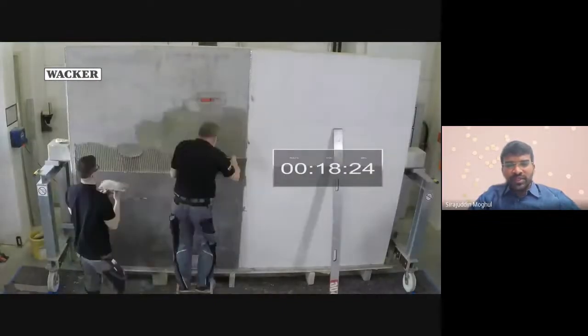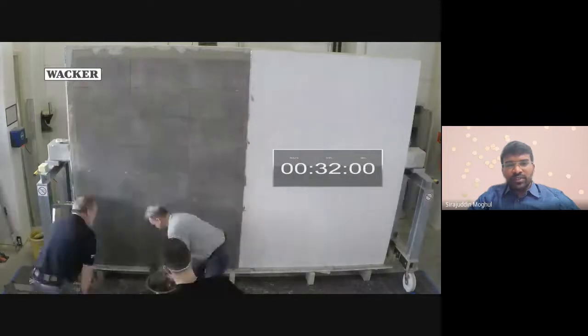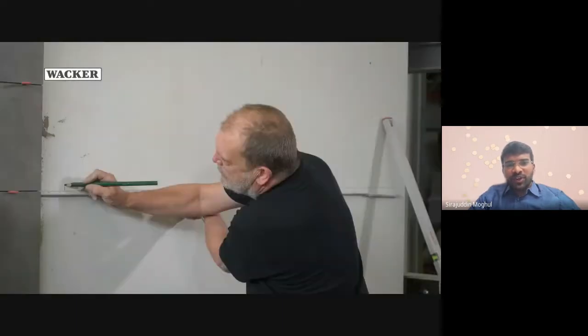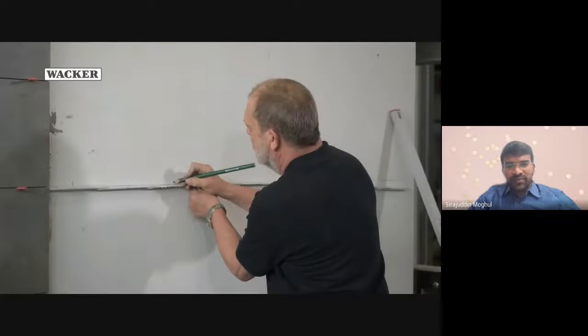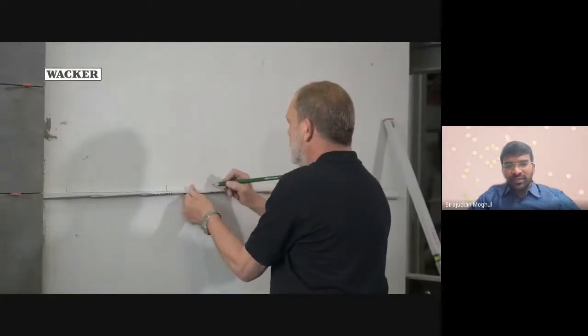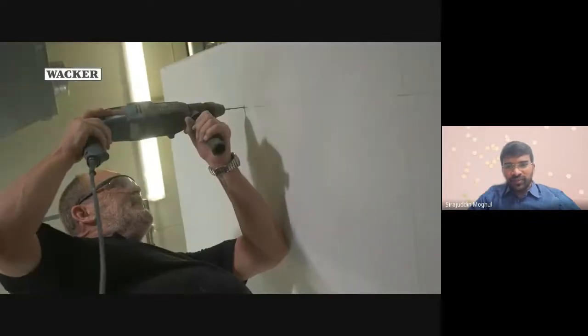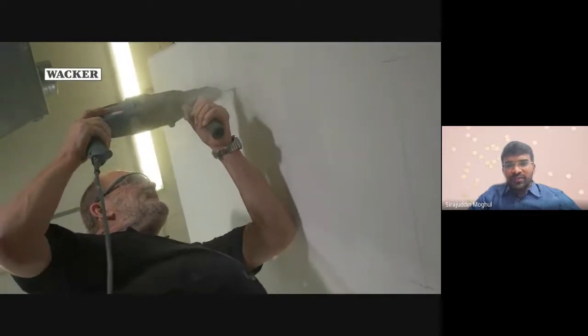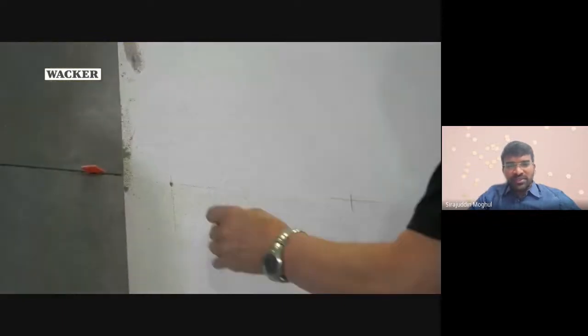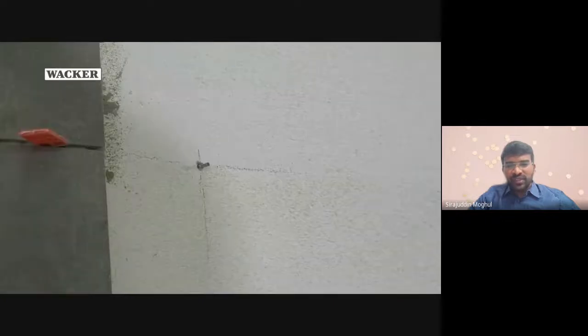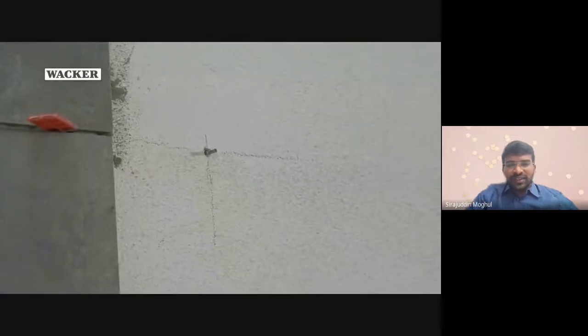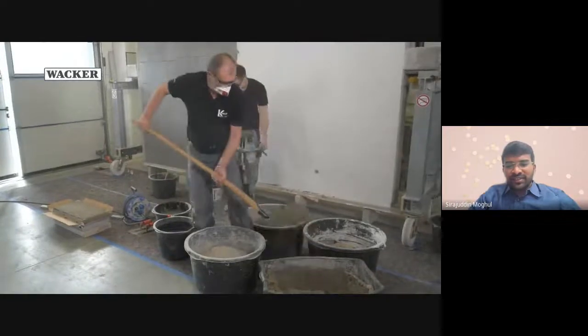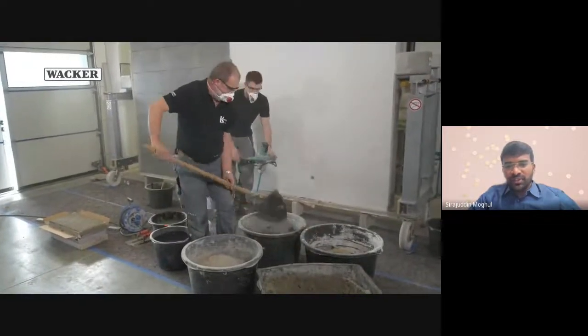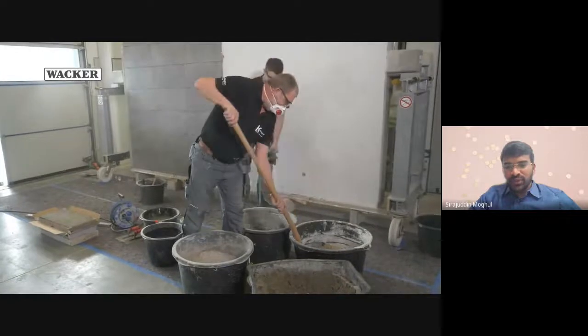So it's very simple, and you can adopt the tiling technology very easily with the thin bed method. On the other side, the same workers are trying to construct wall tiles with the thick bed method. If it's a dry board and we need a plaster, we first need mortar, which has to be prepared, and it is very difficult because we don't know how much sand to use,